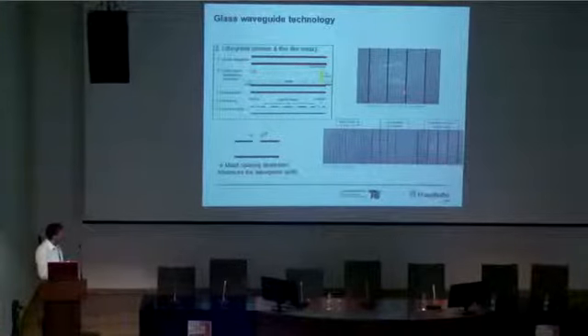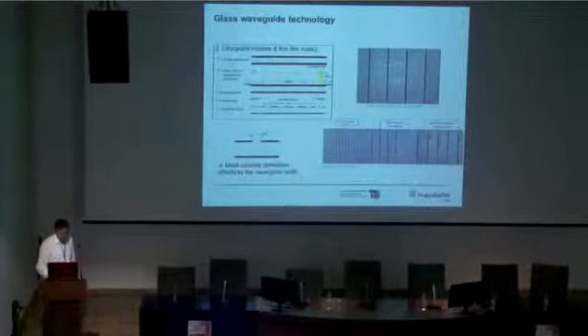We can also control the pitch of the waveguides in this step and define the waveguide width, because this influences the diffusion process afterwards. Then we put these glass panels into a furnace. Such a furnace is not available on the market, not for this kind of process. So we have developed such a furnace at Fraunhofer, and here the benefit is, of course, because we use a thermal process, we can really process lots of panels in parallel. The panels will be vertically placed into the furnace, and it's very well suited for batch processing.